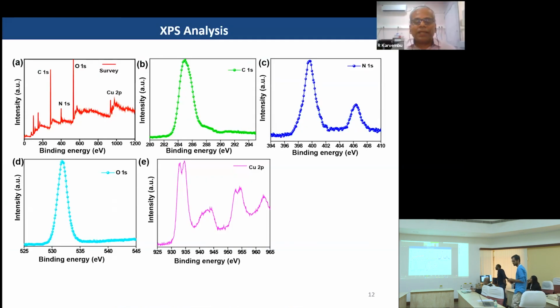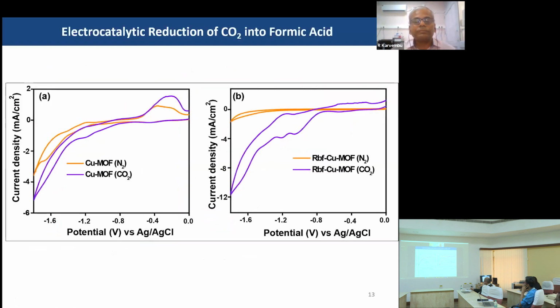From XPS analysis, we could confirm that the oxidation state of copper present in the MOF is +2. Interestingly, in the XPS spectra of the riboflavin-modified copper MOF, the photo emission peak at 933 electron volt is clearly split after modification with riboflavin, which gives an idea that the copper ions present in the MOF interact with riboflavin. But there is no such split observed in the case of the pristine MOF.